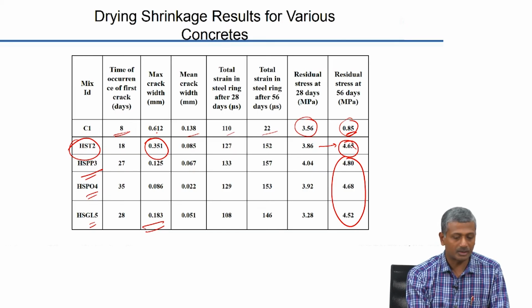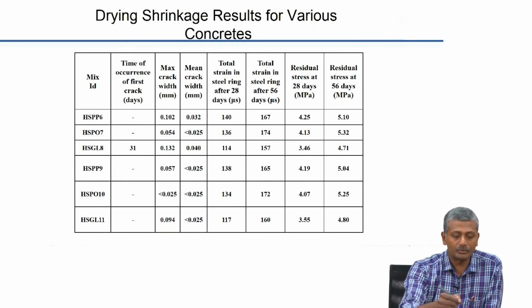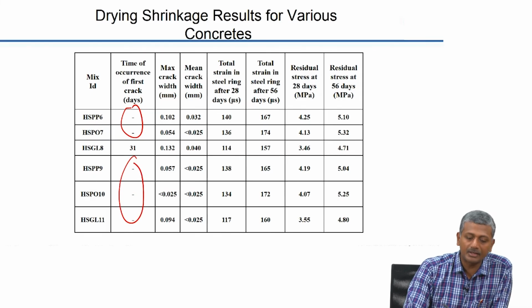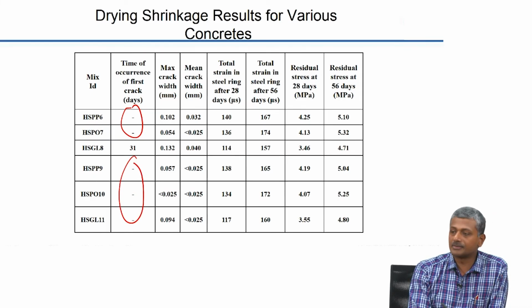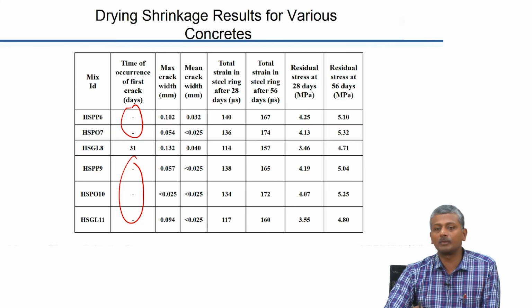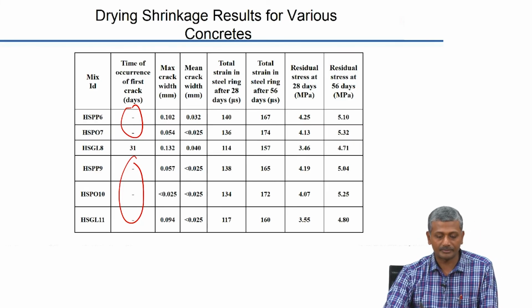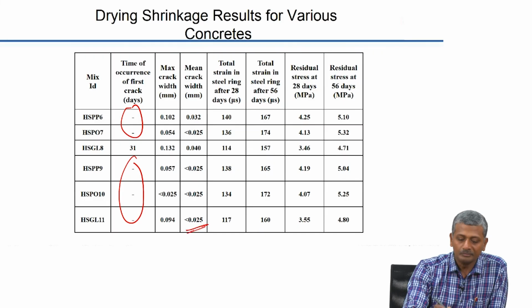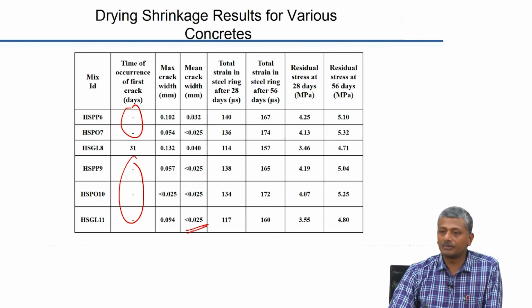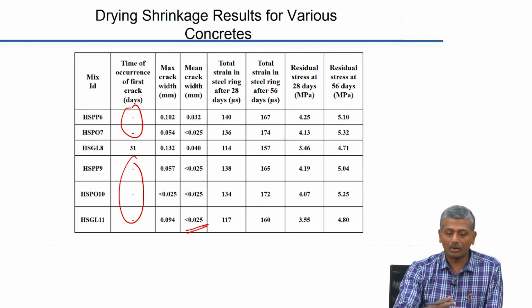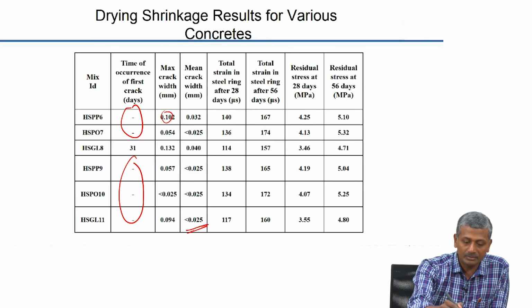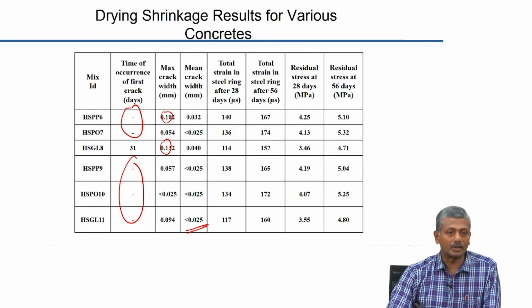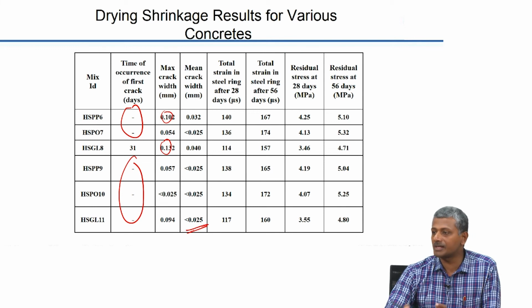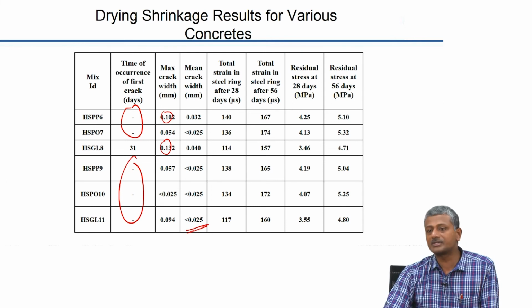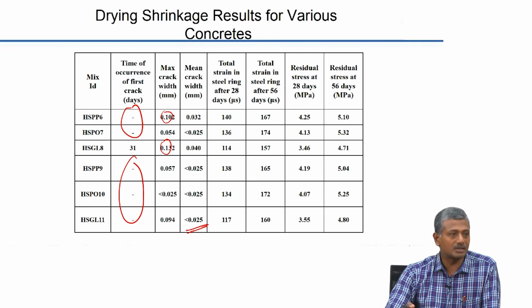That means the polymeric fibers and the glass fibers are contributing in a big way to the restriction of cracking during drying shrinkage. Again, when you see a dash, that means that no cracking was seen in these systems, which have a higher extent of the polymeric and glass fibers as opposed to steel fibers. Okay. And the mean crack width is very low in many of these cases. So, even the maximum crack width only in some cases is greater than 0.1. So, the hybrid combinations are actually leading to a condition where crack widths can be controlled tremendously. So, you have a significant improvement of the ability to resist drying shrinkage cracking.